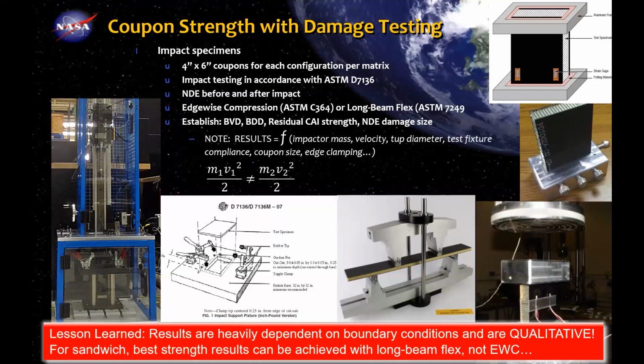And in that instance, for a tool drop, 1/2 mv squared does not equal 1/2 mv squared when the mass and the velocity change. And we've done some work there to show that if you're dropping a tool and that's your real threat environment, you should probably get that right. And in this instance, we've got a custom design impactor that allows us to drop basically the mass of a tool, 1 or 2 pounds. Vastly changes the kind of damage.